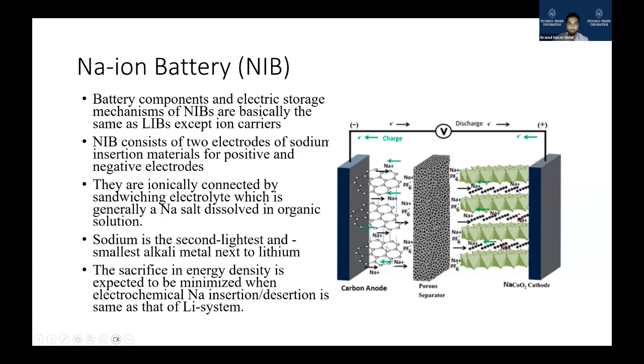And then sodium is intercalating this time with carbon, and it is a similar process. But the thing is, now we need to get a higher distance between these graphite plates. Previously, we saw that lithium is very small, so it can fit inside this hexagonal structure. But now this sodium needs to be inside the plate, because graphite has moving plates, and this moving plates distance is higher than the distance inside this hexagonal structure. So sodium is now being inserted inside this structure, which is graphite moving structure, and the number of sodium that can be stored is less.